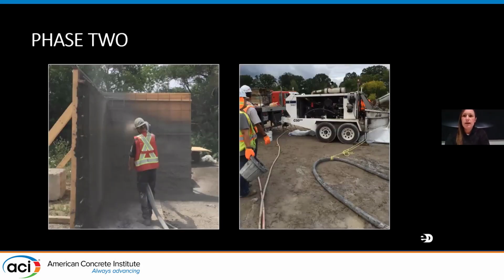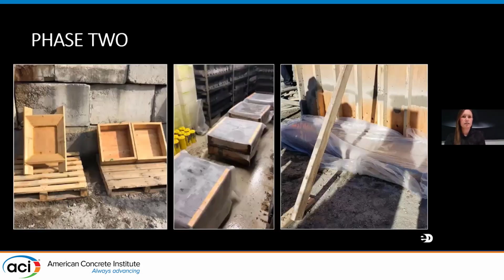Moving to phase 2, we had constructed a production-like mock-up to demonstrate the pumpability, shootability, and finishability attributes of the shotcrete mixes, simulating a similar length pump line as we could expect on site, which was about 60 meters of line. One trial was held at a ready-mix supplier's yard, and the other was held on one of our downtown Toronto projects. Samples were shot into wood test panels for hardened property testing, which we did compressive strength by taking cores, drying shrinkage by saw cutting prisms, boiled absorption and volume of permeable voids, and RCP as well.